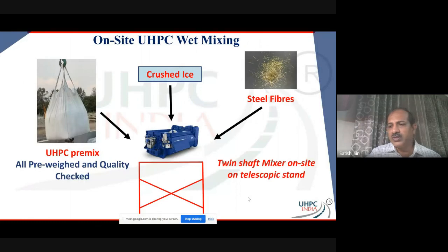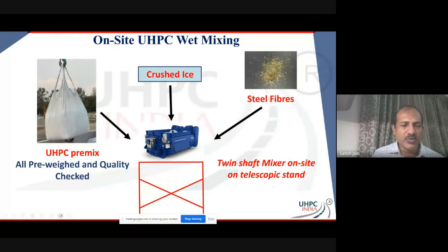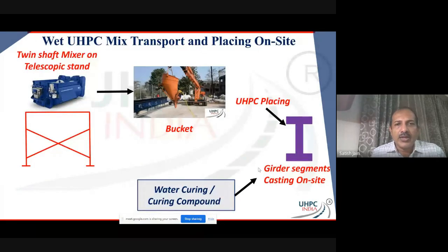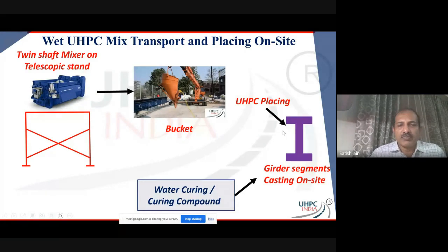On the construction, I just want to show one little slide over here. On a job site, if you're getting a jumbo bag, you just have a mixer that needs to be put on top of a telescopic stand. You put crushed ice in it and add the steel fibers, and then you can have a bucket down below, or you can have a pump down below through which UHPC can be moved into wherever it needs to be placed. So on site, it could be a very, very simple mechanism. There it shows. The bucket's there, and the bucket will take it to the beam and just pour it into the beam.